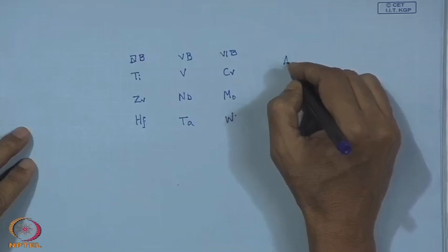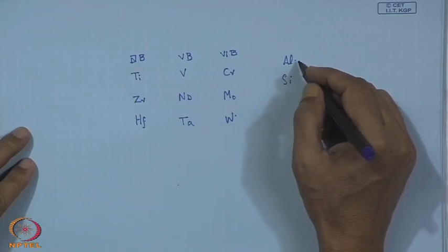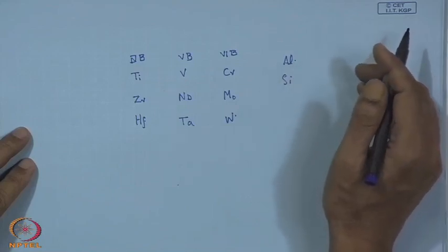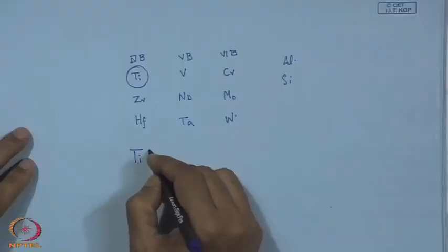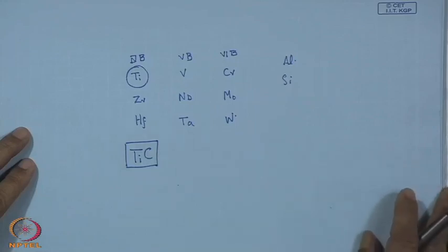In addition to these nine elements, we can also add aluminum and silicon, because their carbide, boride, or nitride can also give such properties. Titanium is especially popular — titanium carbide has tremendous success in offering such properties, particularly in forming tools and cutting tools. A TiC coating at the top of the tool can raise the tool's lifetime by several times, or even substantially increase cutting speed.